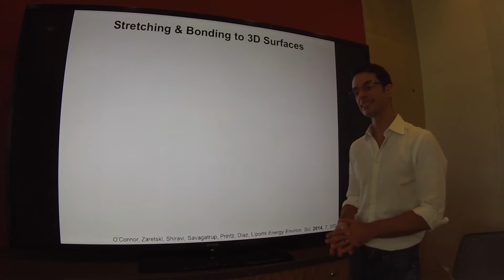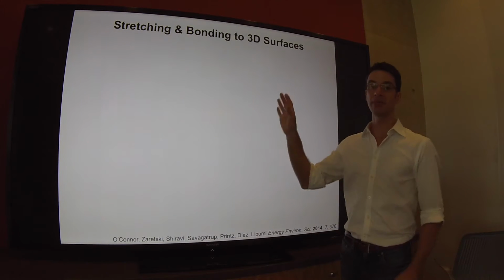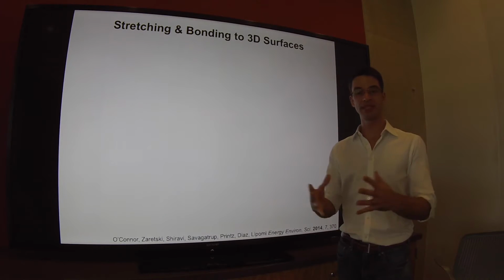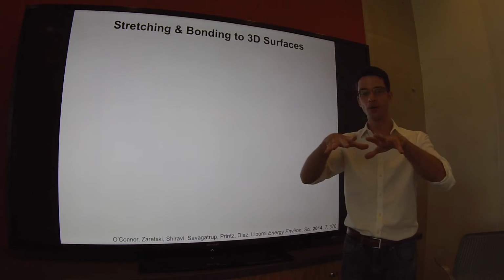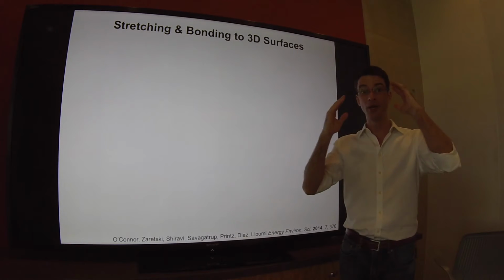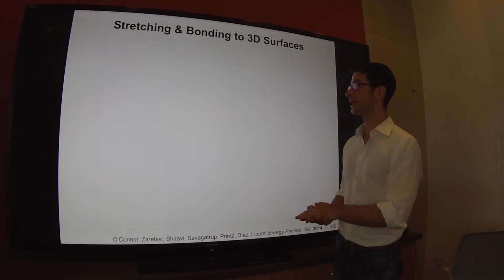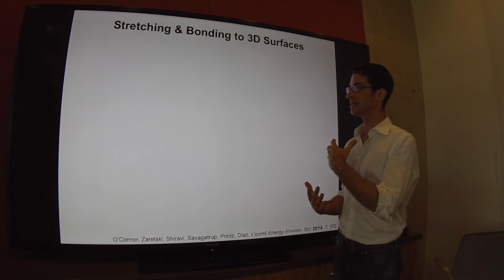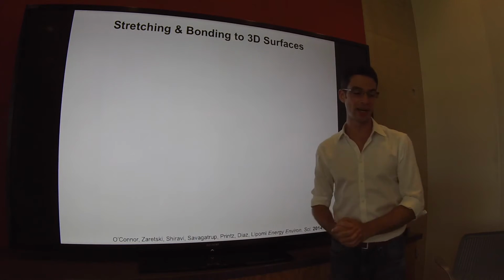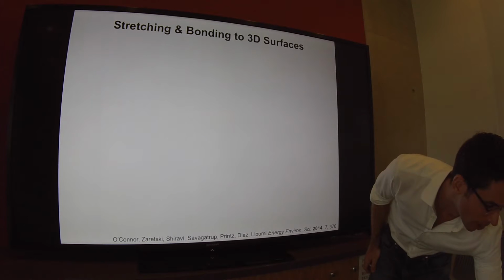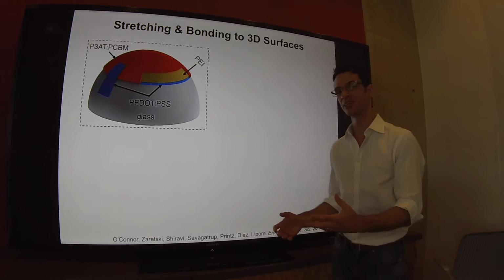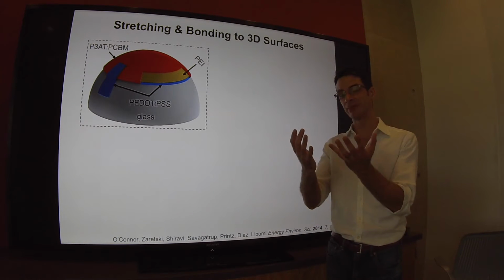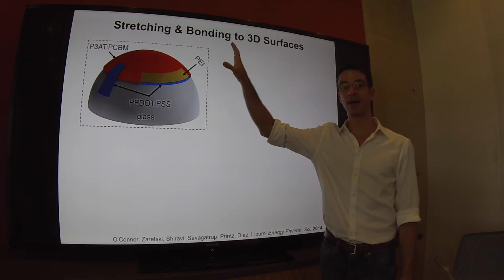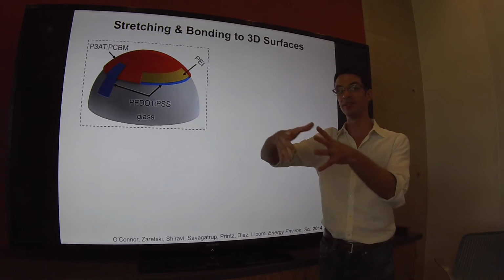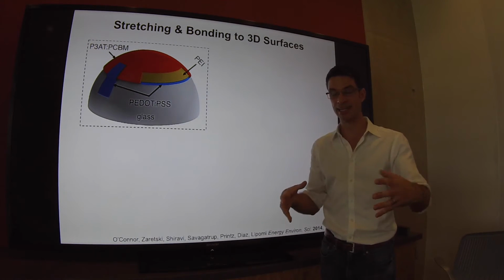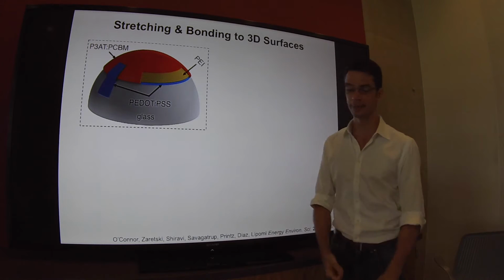So using this knowledge, we can do something just by using the molecular structure. We can take a whole organic solar cell and stretch it over a surface with a complex topography, other than a cone or a cylinder. A cone or a cylinder you can just bend. But if you want to put a solar cell on a hemispherical surface, you need biaxial stretchability, not just bendability.